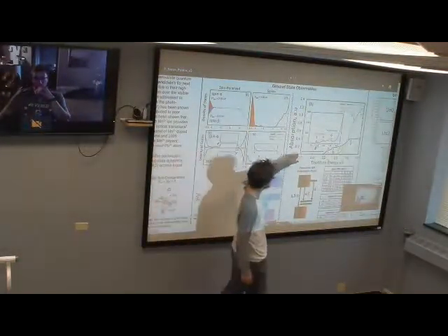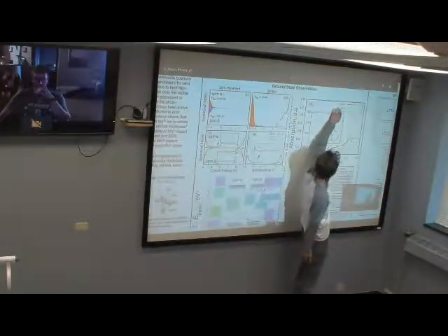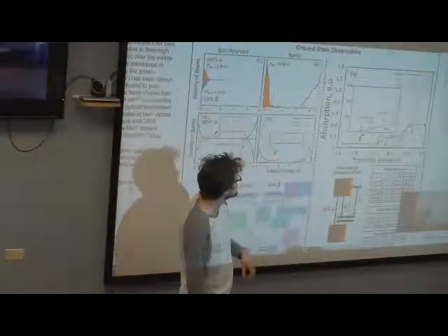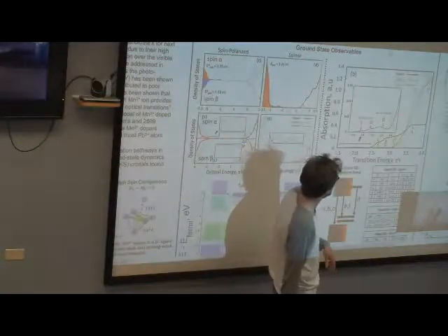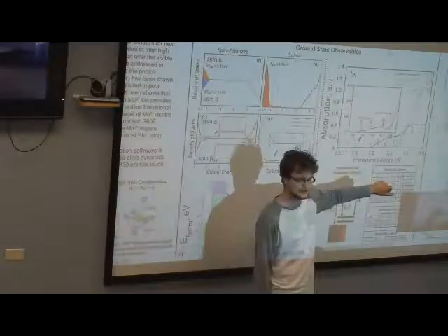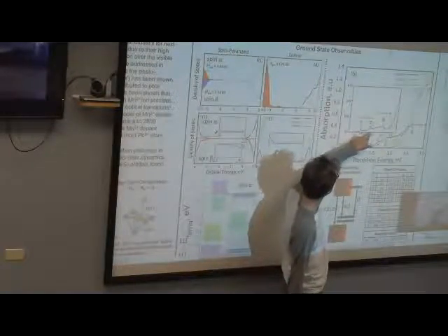So we trudge along even with the qualitatively incorrect valence band. We can still go through and try to compute the D to D transitions. So here in this big plot is an absorption spectra comparing the spinor orbitals, which is the solid red line, and then the spin polarized are the dashed orange and green. The big takeaway here is if we zoom in on these low energy transitions, which are about an order of magnitude less than absorption from the perovskite quantum dot,